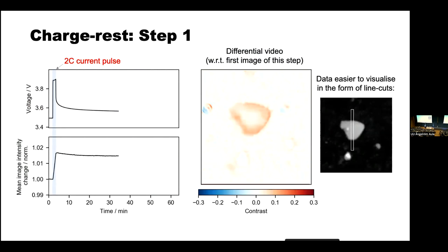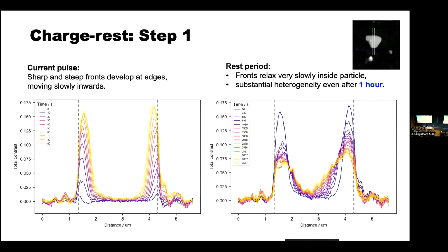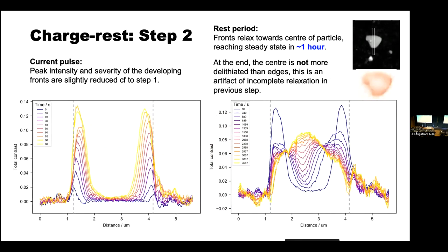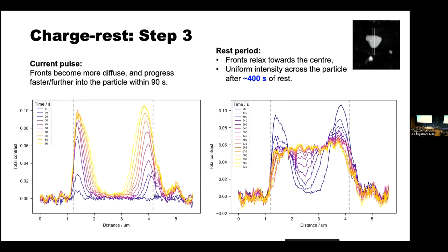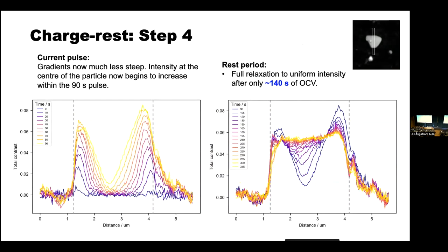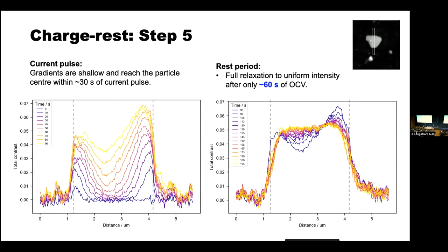I want to now individually analyze each step of the process. In step one, the one I've just shown you, this is the current pulse. You pull lithium out of the edge of the particle, and then you sit there for an hour, and even after an hour, it hasn't reached equilibrium. Then you pull the next set of lithium out. You can see in the current pulse, again, you're pulling lithium from the edge, and it takes about an hour to reach equilibrium. Then you take the next one out. You can do it now in 400 seconds. The next one you can do in 140 seconds. And the last one you can get at about 60 seconds.